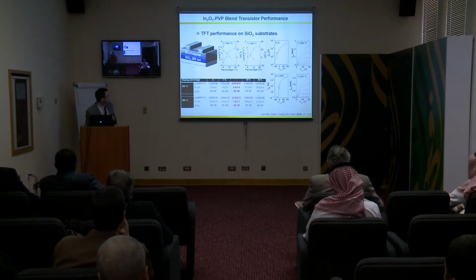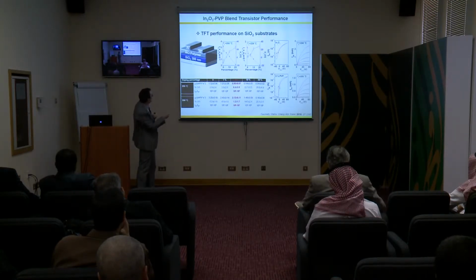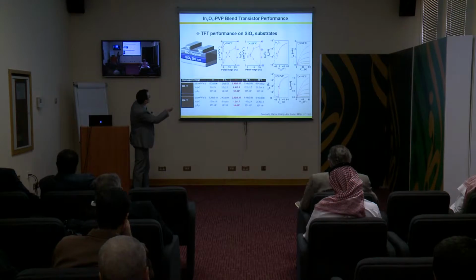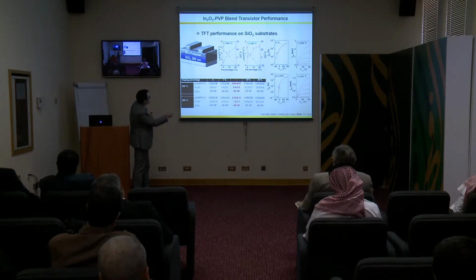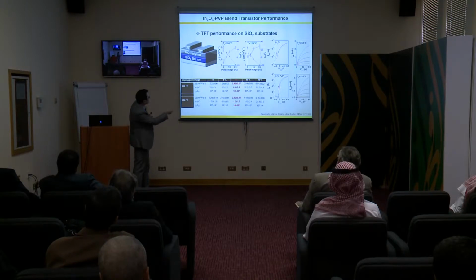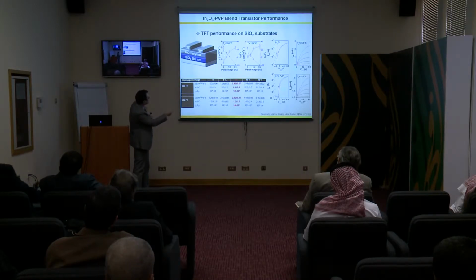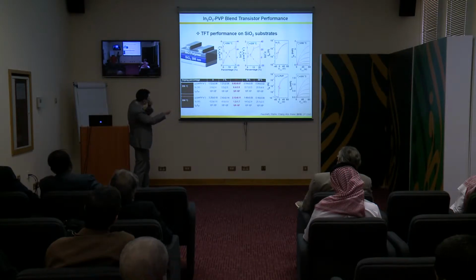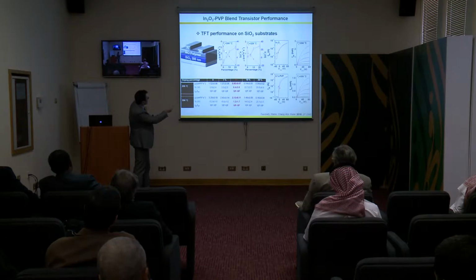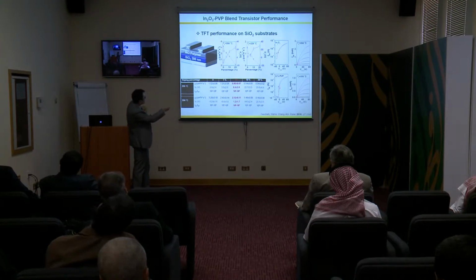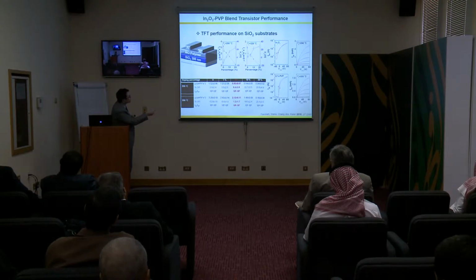And then we started making devices. To make the story very short, let's look at this data. Here is the field effect mobility, and this is with the percentage of doping with the insulating polymer. The red is the mobility, and you see that the mobility does drop when we start adding the polymer, but there is a sort of regime, on the order of between 1 and 5%, where the mobility remains quite large. The threshold voltage, which is also another important parameter, remains very close to 0, which is very good as well. And the processing temperature is acceptable. So there is really a regime where we get amorphous phases characterized with quite decent electron mobility. And here are mobilities on the order of 2, okay?